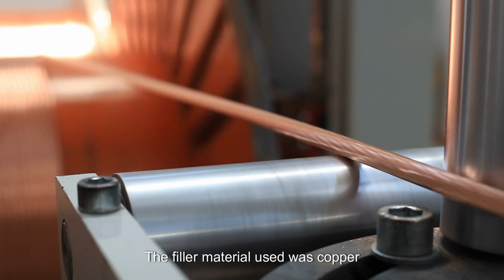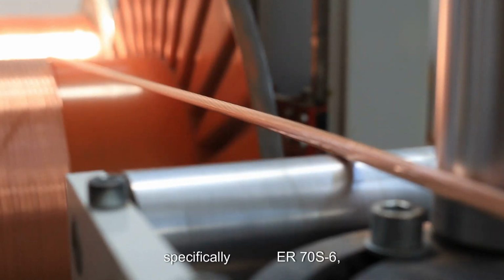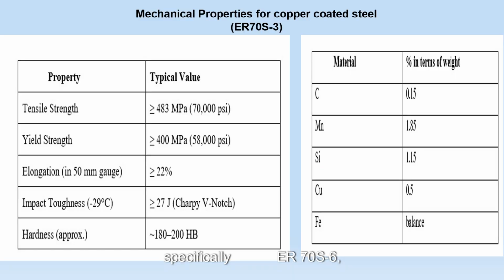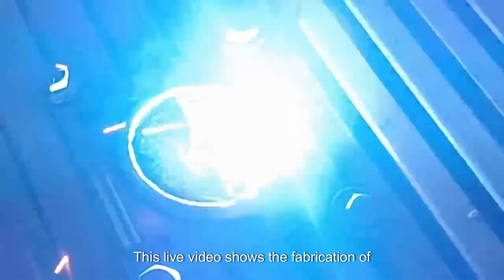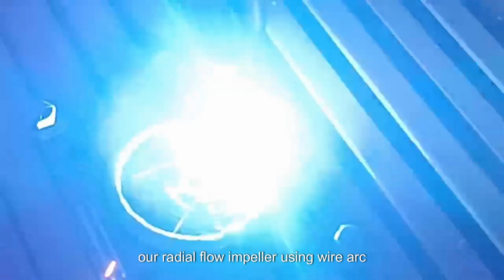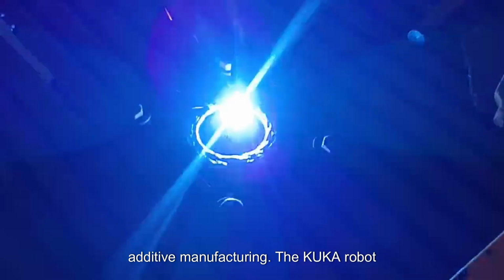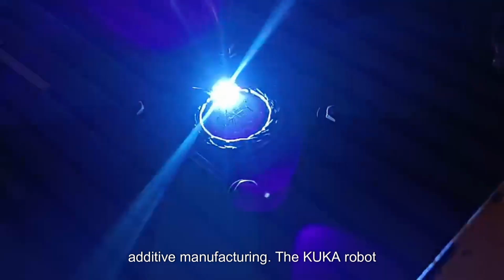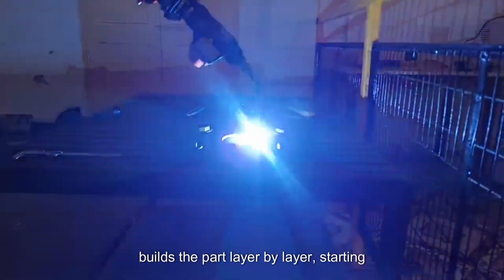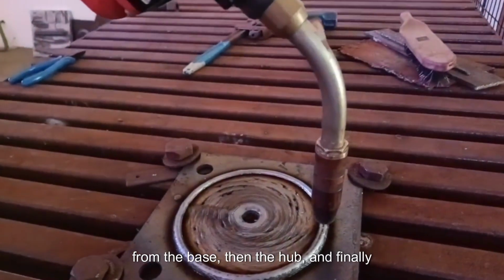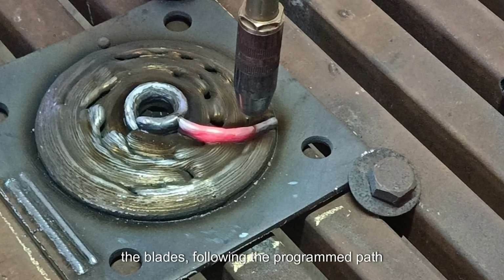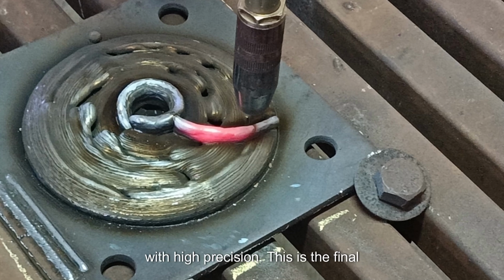The filler material used was copper-coated steel wire, specifically ER70S6. Chosen for its excellent arc stability, low spatter levels, and suitability for high deposition processes like WAAM. This live video shows the fabrication of a radial flow impeller using wire arc additive manufacturing. The KUKA robot builds the part layer by layer, starting from the base, then the hub, and finally the blades, following the programmed path with high precision.